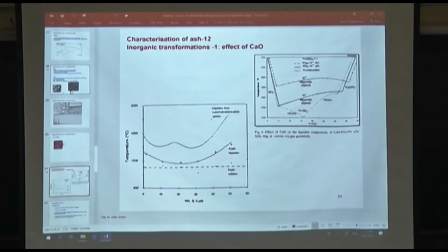You can find that easily. These days it's really, really easy. So say for example, you have a starting composition. In the second composition, you increase calcium oxide by 10% and reduce everything else by 10%. In the third sample, you increase calcium oxide by 10%, but reduce the others in different ratios. You will get a different series of results from which you should be able to draw this type of graph.